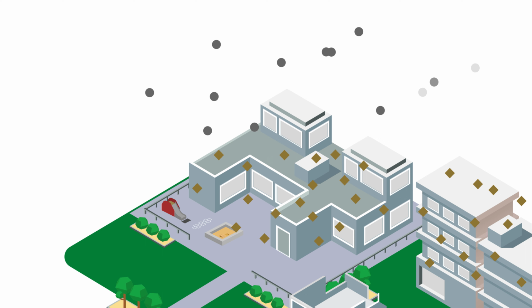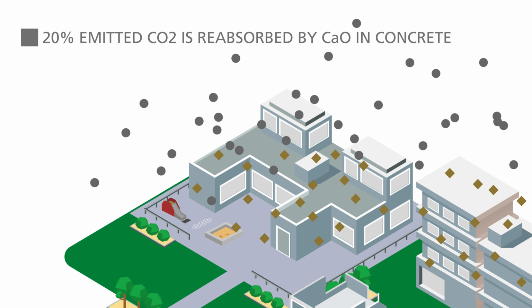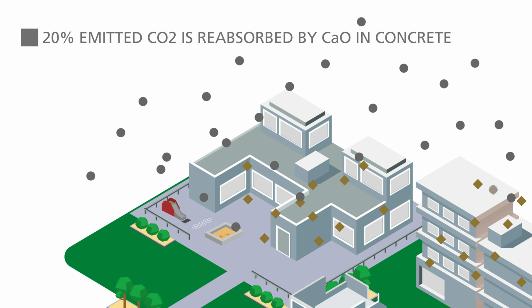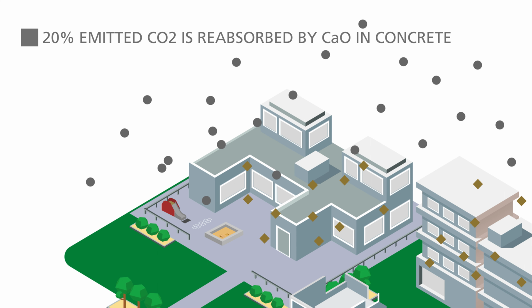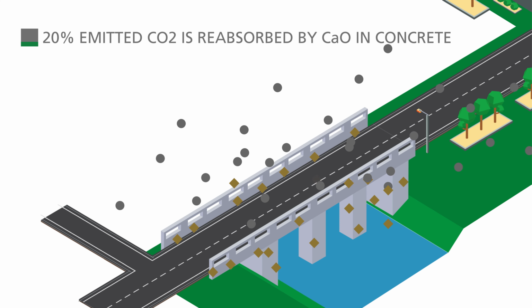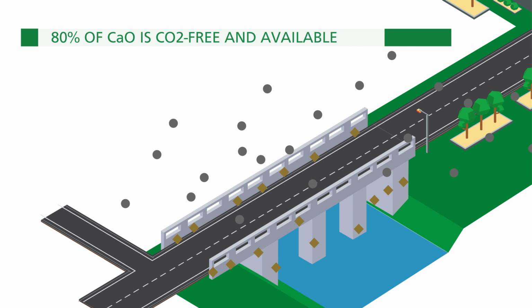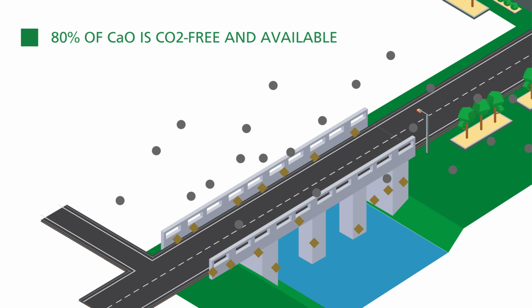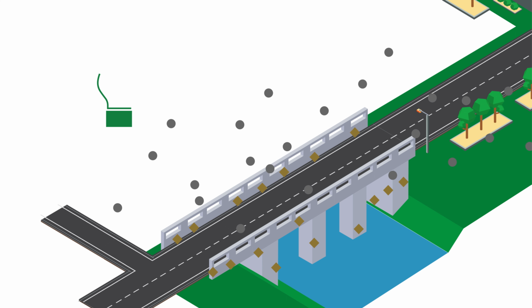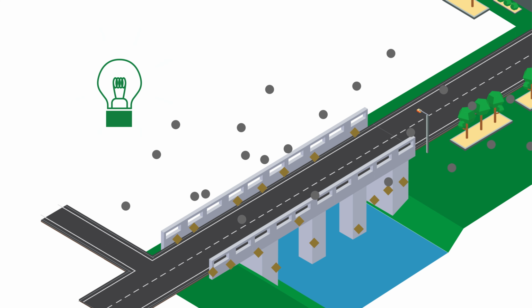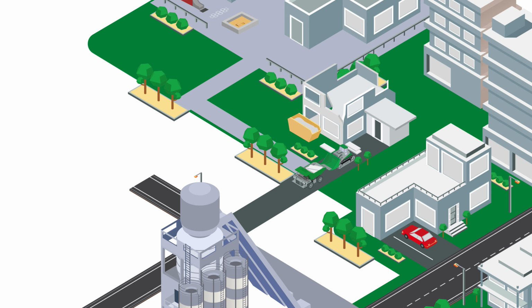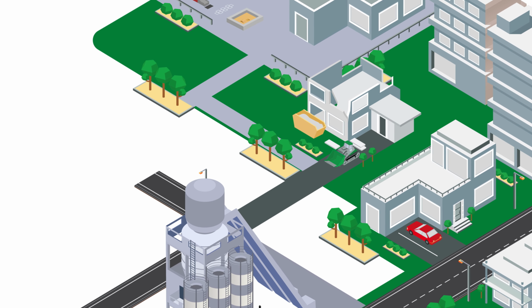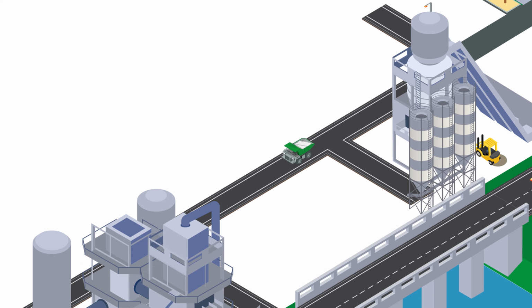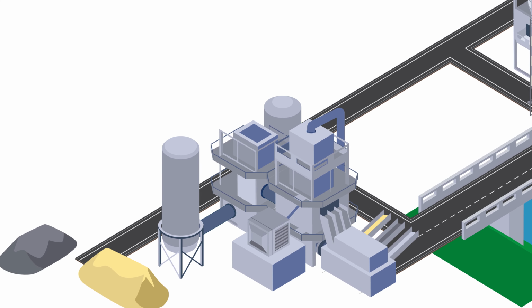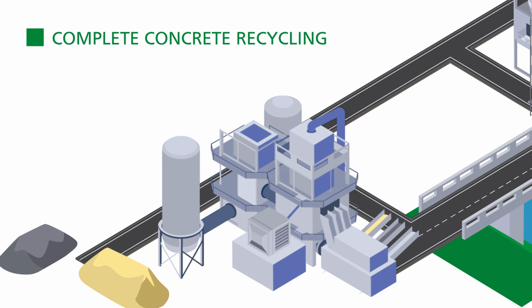An average 20% of the CO2 emitted during the calcination process will be naturally reabsorbed during the lifetime of various concrete products or structures that are exposed to air. However, even the remaining non-carbonated 80% of the calcium oxide can be utilised to reduce CO2 emissions. Learning from the natural chemical reactions, HeidelbergCement developed industrial technologies to give new life to used concrete through a CO2 negative process. There is a huge opportunity in recycling demolished concrete.